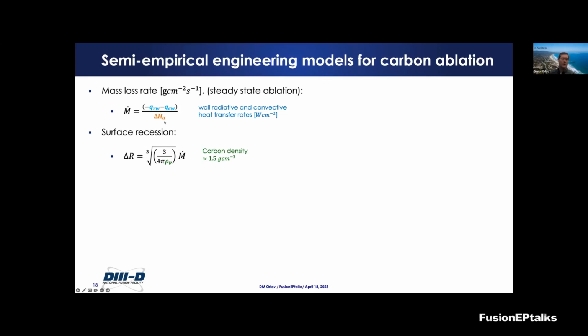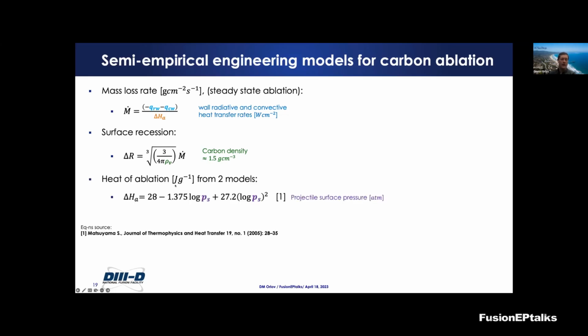That's where the semi-empirical models come in, because once we know this value, we can calculate the mass loss rate, and from the mass loss rate, we can calculate the recession rates on the surface of our stationary rods or little pellets. So there were at least two major models that were created after Galileo's probe.